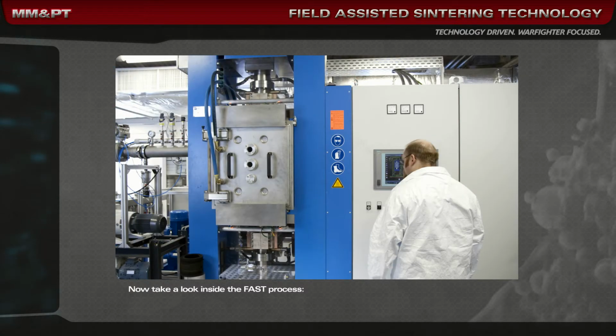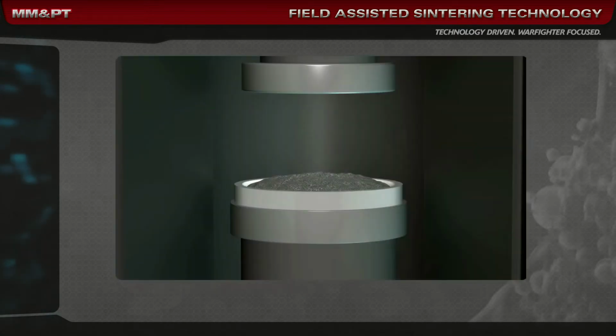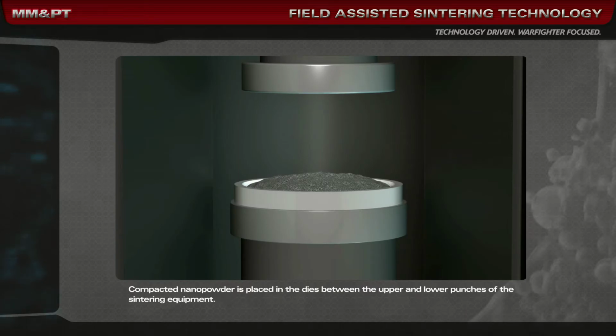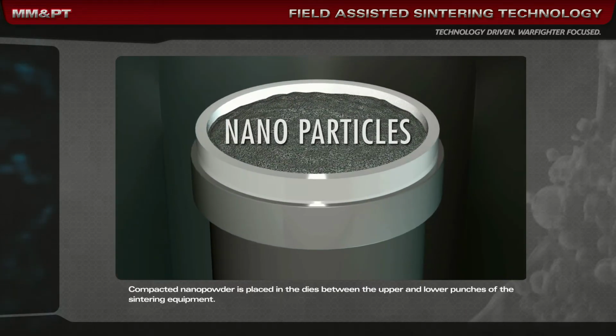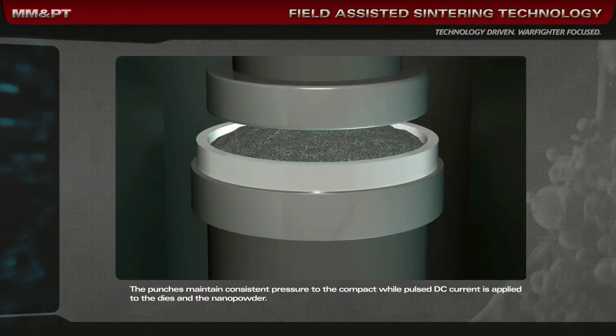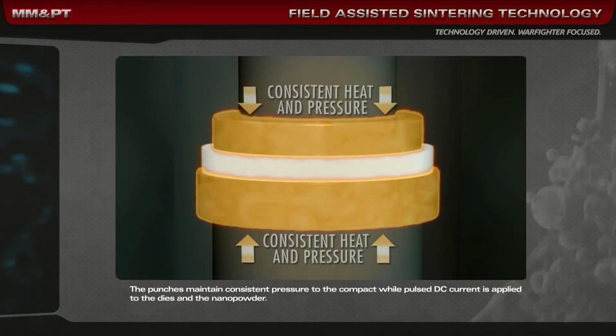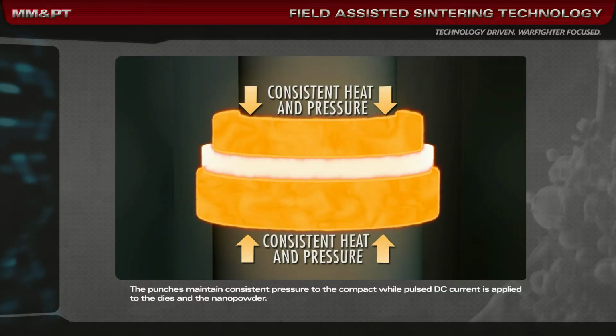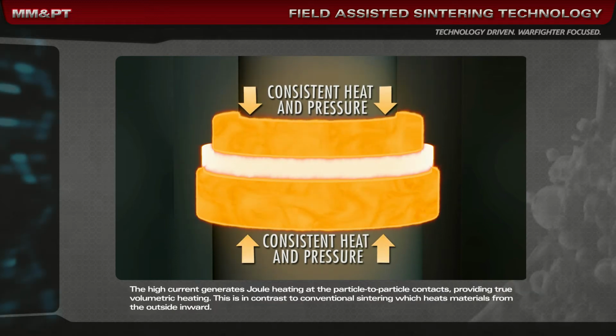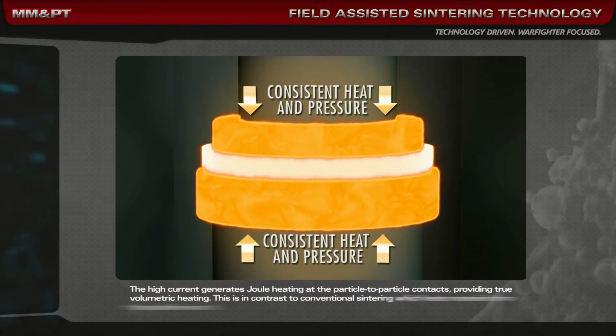Now take a look inside the FAST process. Compacted nanopowder is placed in the dies between the upper and lower punches of the sintering equipment. The punches maintain consistent pressure to the compact while pulsed DC current is applied to the dies and the nanopowder. The high current generates joule heating at the particle-to-particle contacts, providing true volumetric heating. This is in contrast to conventional sintering, which heats materials from the outside inward.